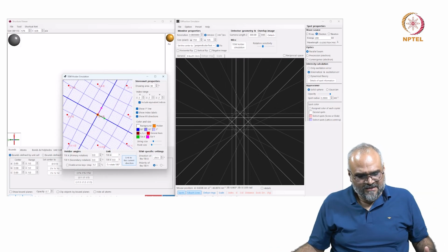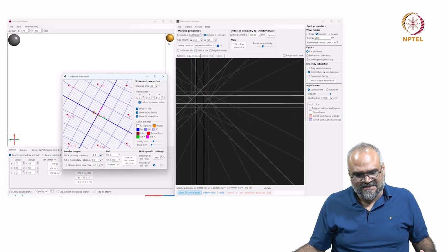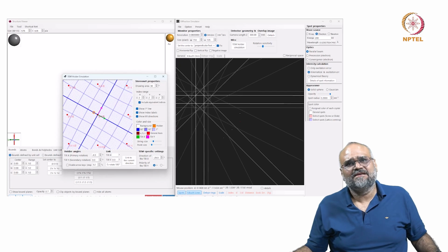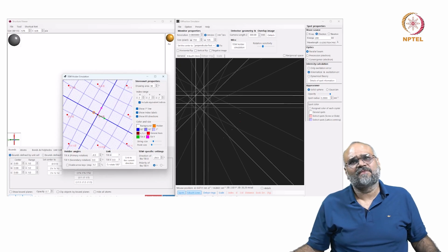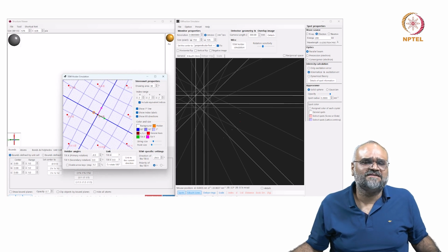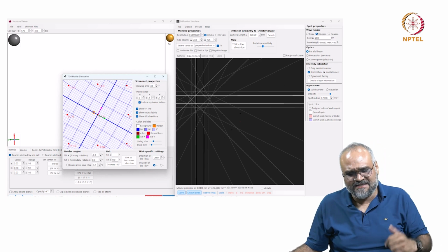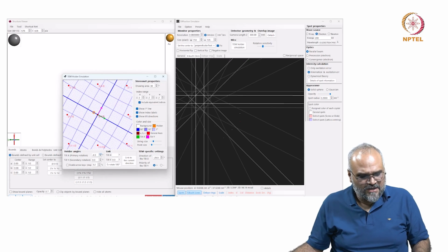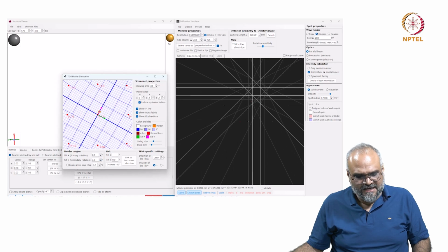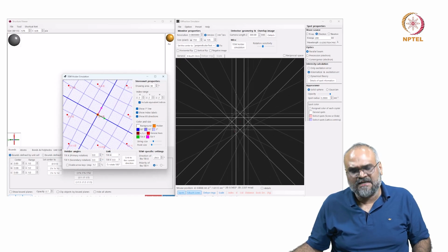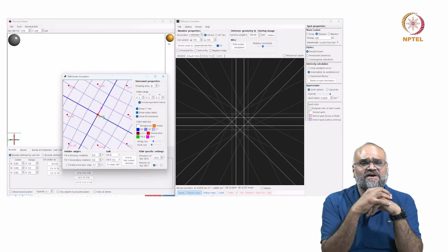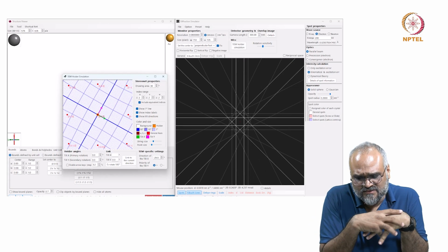So, for example, when I initially have a crystal which is somewhat randomly oriented and I see some spot patterns like this, and if I converge the beam, if I see a node of Kikuchi bands like this, by tilting the holder in particular directions, I can actually bring that node to intersect with the central bright spot, and this is what I am doing when I am doing orientation of a crystal along zone axis in the microscope.